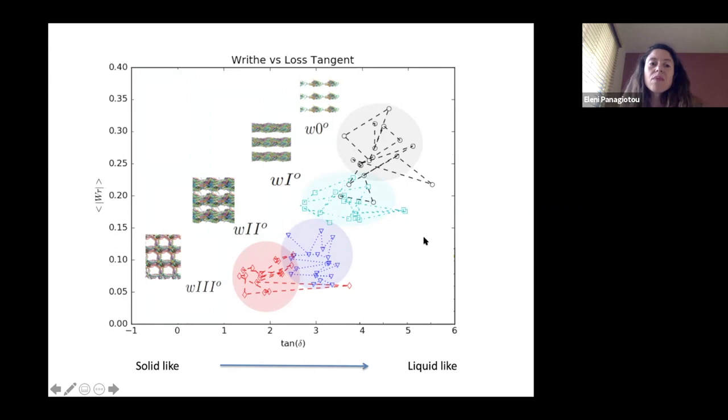That might seem counterintuitive in general, because you would imagine more complexity, meaning more writhe, meaning more solid-like response. But I think this result here is because of how we started the system, and because it is a solution, so that when there is enough space for the chains to disentangle and attain higher writhe, just because they can attain conformations like those of random walks, let's say. They are unconstrained conformations. So they tend to values, they don't have to be extended by entanglements with other chains.